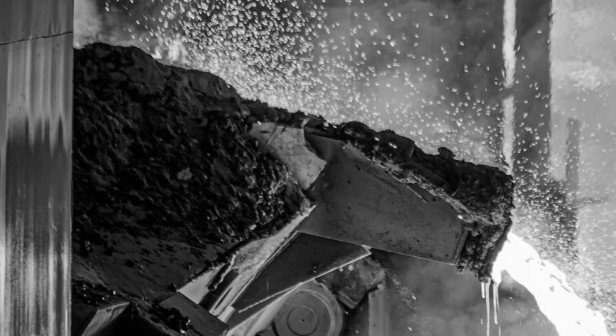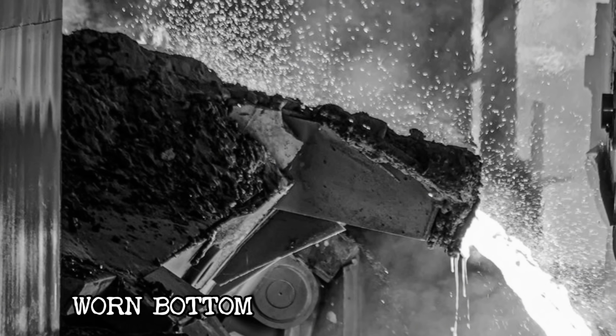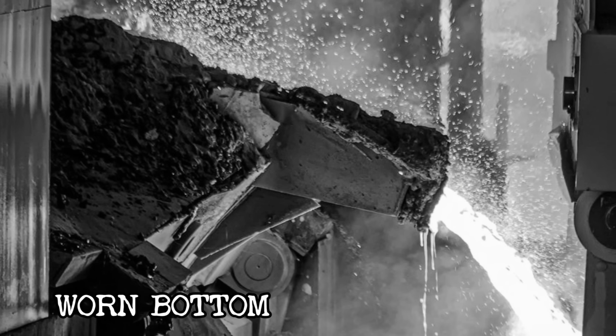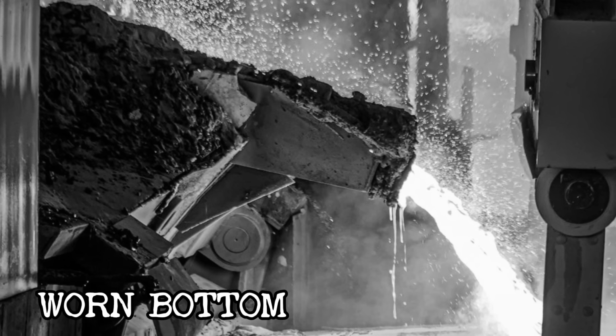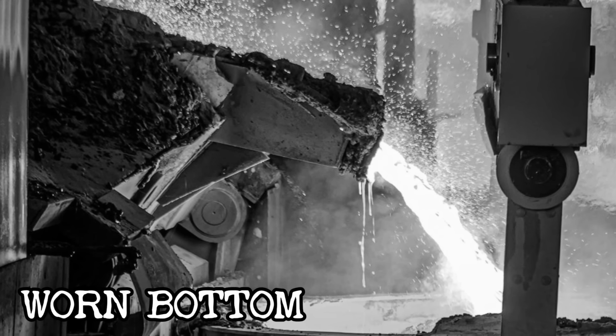The converter's bottom, the detachable plate fitted with the air holes, simply wore out. The intense heat and constant chemical assault degraded it faster than almost any other part of the machine, and a worn bottom didn't fail gently. It failed by letting molten metal break through where it shouldn't, sometimes with almost no warning.